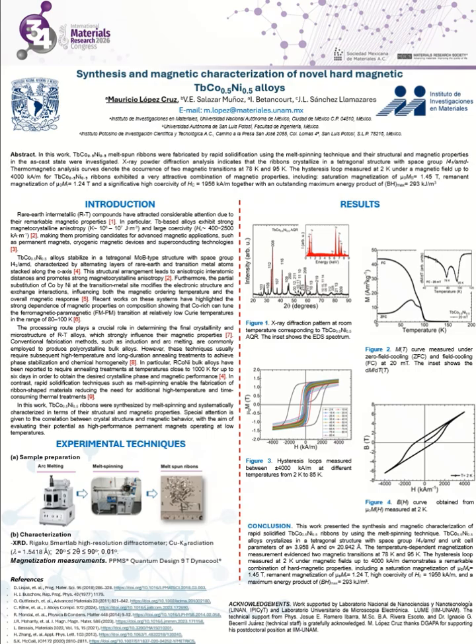In this work, these alloy ribbons were synthesized by rapid solidification, specifically with the melt spinning technique, providing a simple and efficient route to obtain a highly crystalline material with outstanding hard magnetic properties, including high coercivity, large remanence ratio, and high maximum energy product. These characteristics make these alloys a promising candidate for next generation cryogenic permanent magnets.